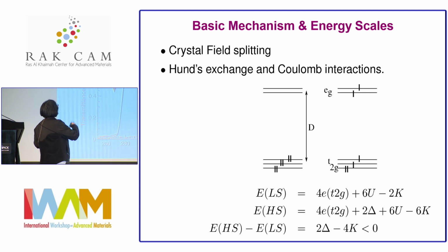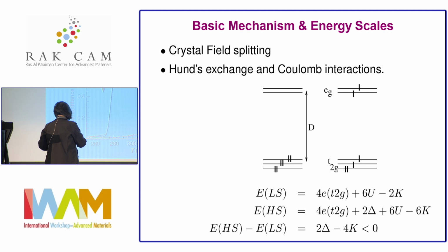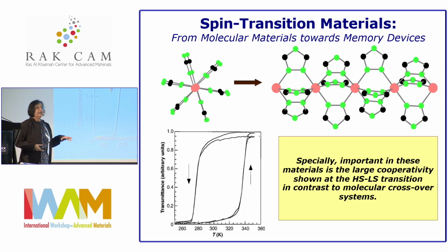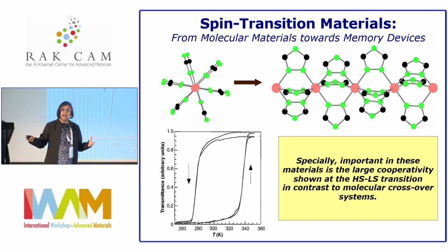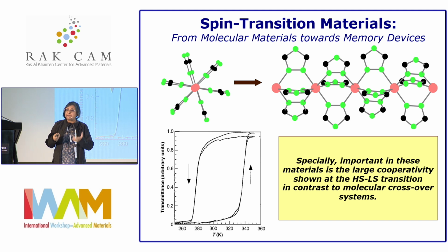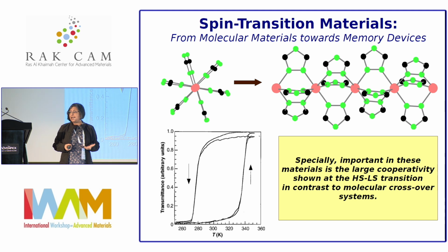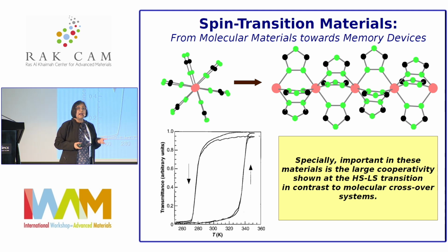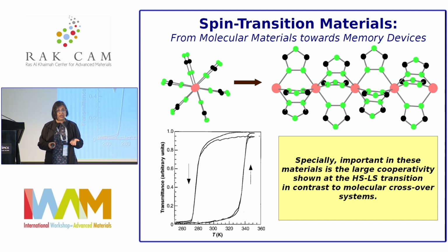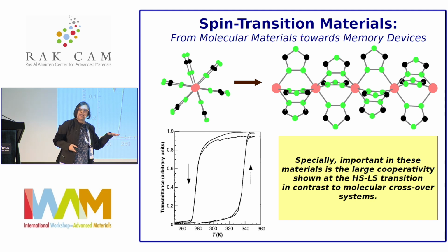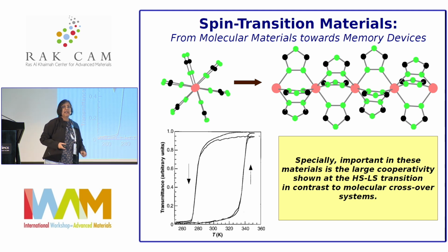Yeah, so the whole idea is, can we make this phenomenon cooperative? That means the spin crossover that takes place at a particular metal site, by putting one of these molecules next to another and making them talk to each other. If this spin crossover happens cooperatively at all metal sites, then this spin crossover, instead of being a crossover, becomes like a transition. And if you can make this spin state transition a first order phase transition, it can actually show up with a very strong hysteresis effect. Therefore, you can use it as a memory device. That's the idea. And the whole idea is, for example, you should have this transition happening at the ambient condition, and make the width of this hysteresis as large as possible. That's the whole idea, if you really want to make an application out of it.